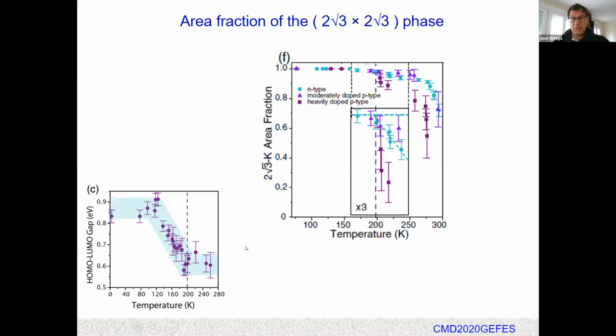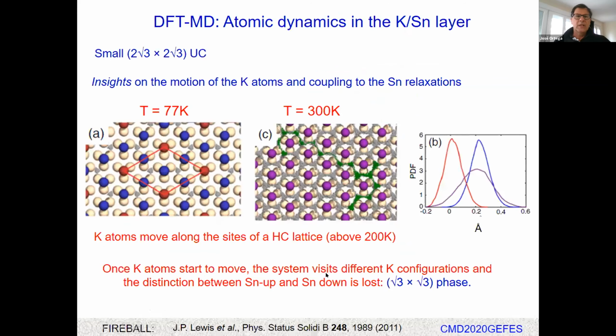And let me stress that the shift in the energy gap that we were observing before with STS is taking place in the region where we have a 100% surface in the ground state. So in this region over here, before 200 Kelvin. Okay.